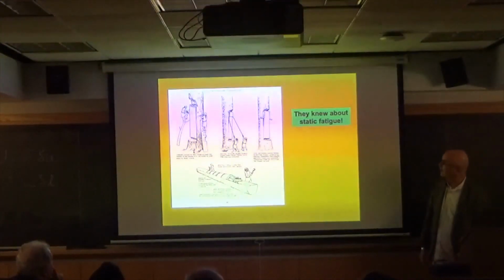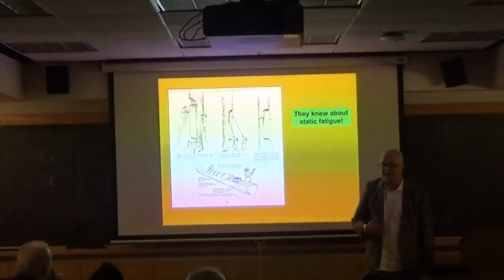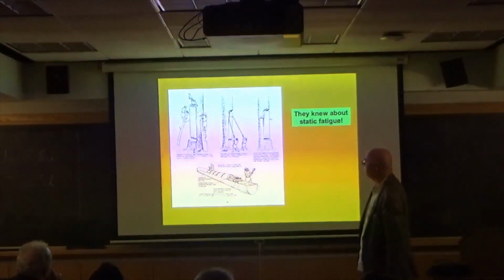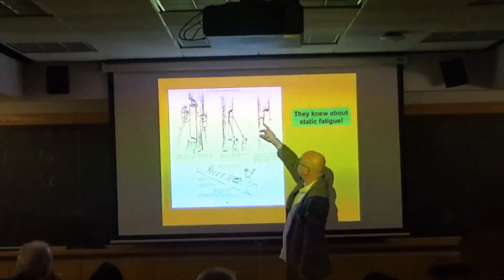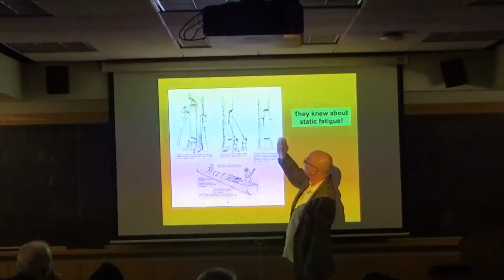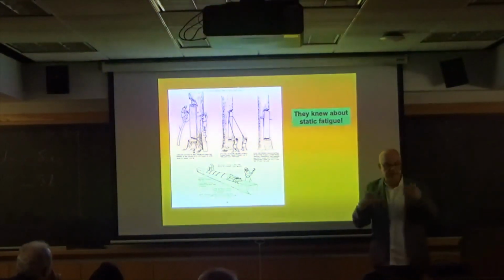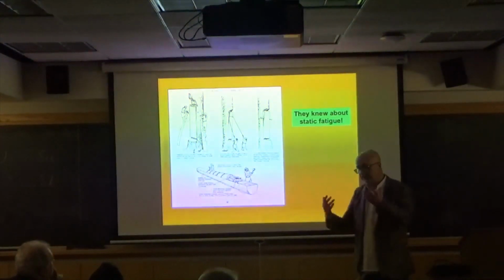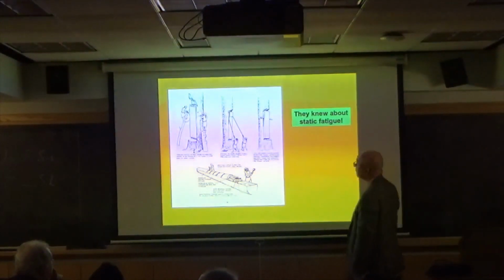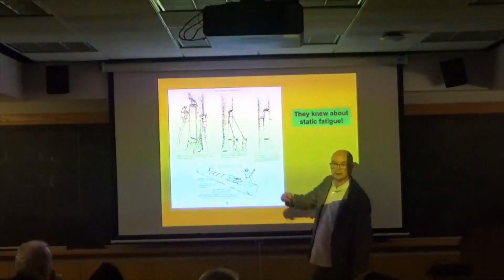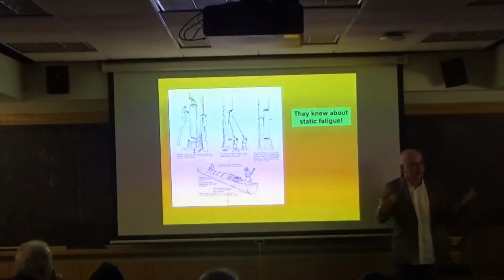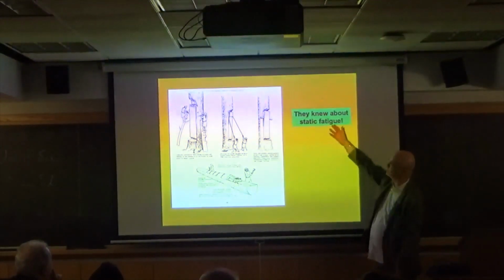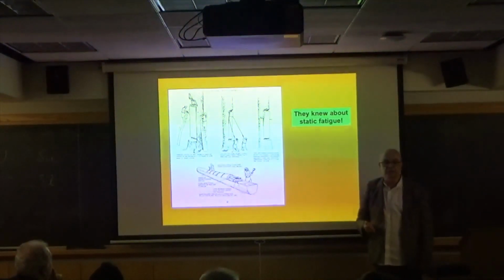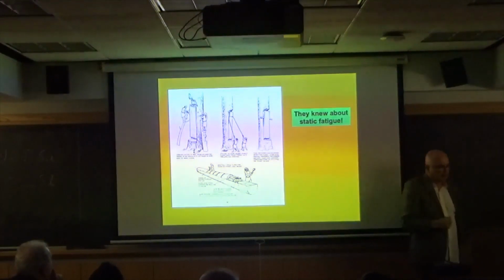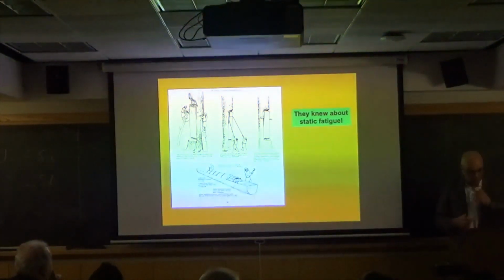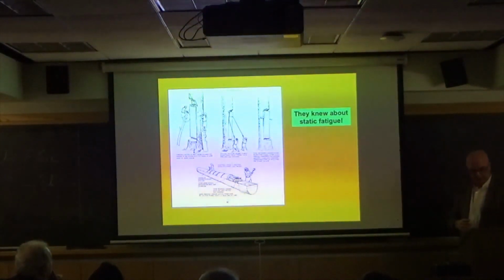They also knew about things like static fatigue, which occurs in glass and ceramics, where they may want to, again, fracture the same kind of plank. So what they do is they put a rod there, they wait, freeze, thaw, environment, water attacking the crack tip and all of that, and then a few months later or a few weeks later, this thing will crack all the way to the other side, and they have what they want. This is what we call today static fatigue or stress corrosion cracking. So they knew a lot about these things through intuition. And this is one of the motivations for the work that we have today.